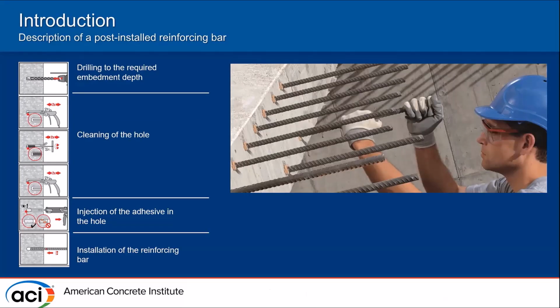So these post-install anchoring systems are basically bars that are glued inside concrete using a structural adhesive. Practically, what happens on the construction site is that for an existing concrete structure, a hole is drilled inside the structure. This hole is then cleaned by air blowing and brushing. A polymer adhesive is injected inside the hole, and then we insert the rebar. And typically, the curing of this polymer adhesive generally takes 24 hours. So at the end, we get a bond system, which is created of the concrete around it, the bar, and a polymer adhesive.